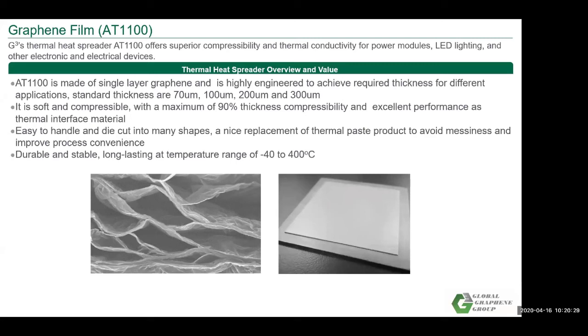We use graphene as the raw material. Graphene is one type of carbon or graphite material. It's quite stable, so it can withstand minus 40 degrees Celsius to 400 degrees Celsius.